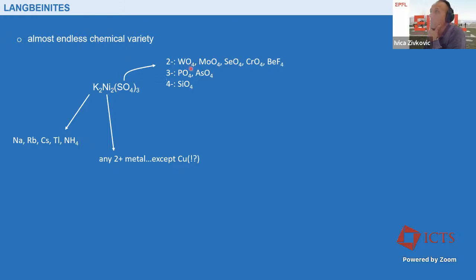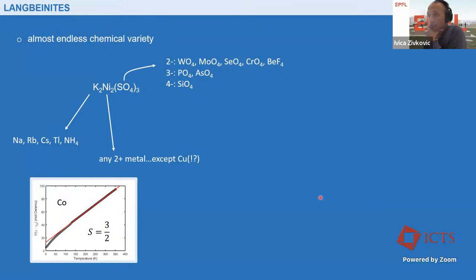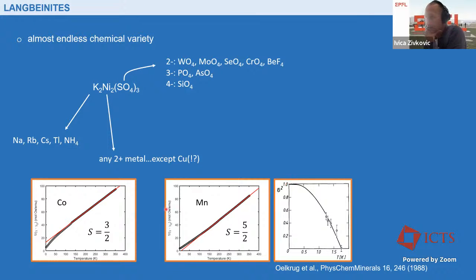And then also the sulfate can be changed. You can see here many other versions which can be squeezed into this structure. We have investigated a couple of them. The cobalt version, and the manganese version, which is one of the rare examples where something has been done and some order has been found below 2 Kelvin. But you can see that the deviation from the Curie-Weiss law occurs at much higher temperature. So the interactions must be much stronger. That indicates that there is a wide temperature range where strong frustration-induced effects might be expected.